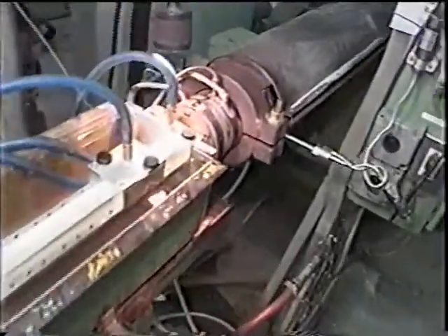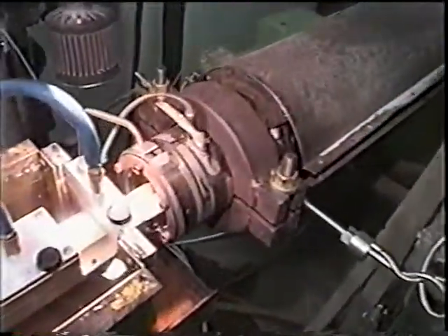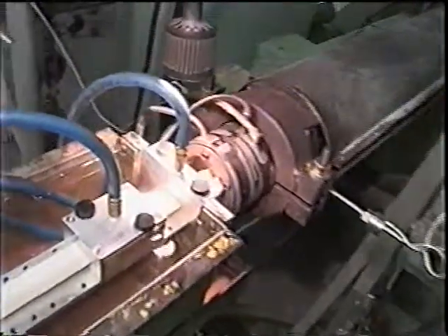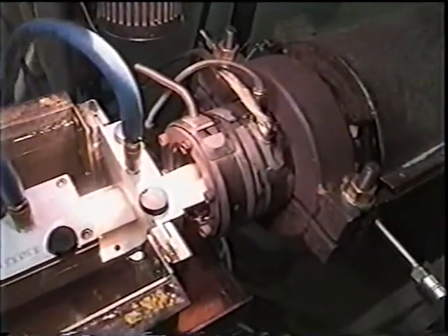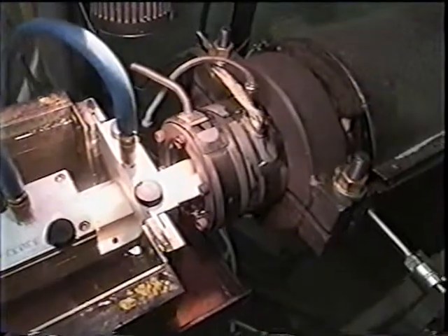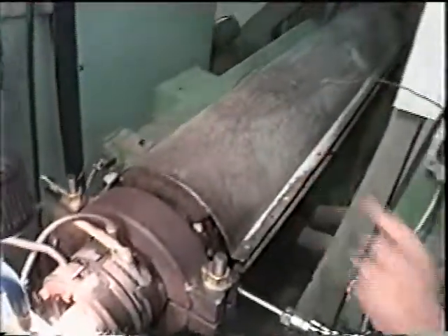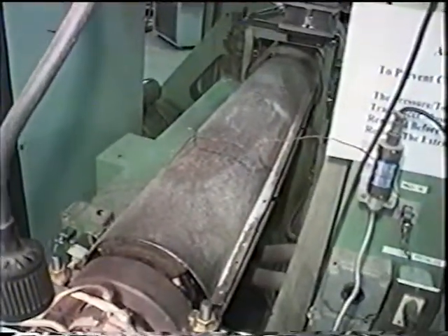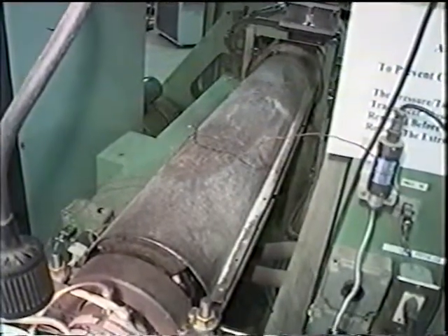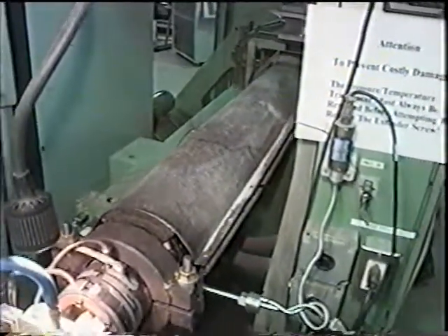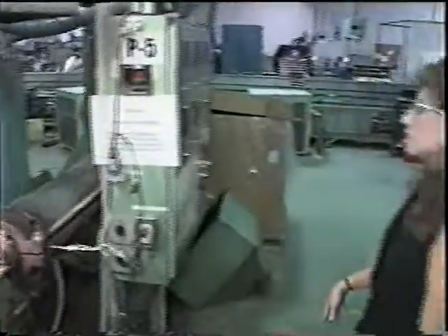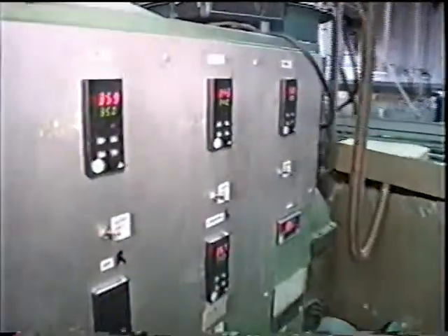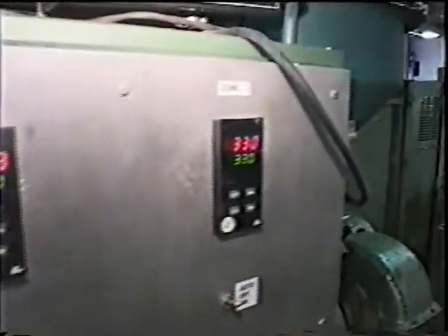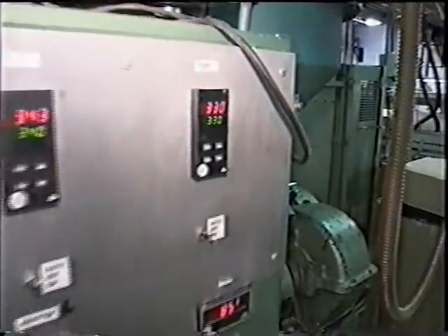This particular ABS resin is run at temperatures of around 350 degrees. The temperatures are controlled very tightly throughout the zones of the extruder barrel, which is back here. The extruder is broken into 3 zones, and the temperature controls to my right are what controls that. We also monitor the temperature of the die and the adapter equipment.